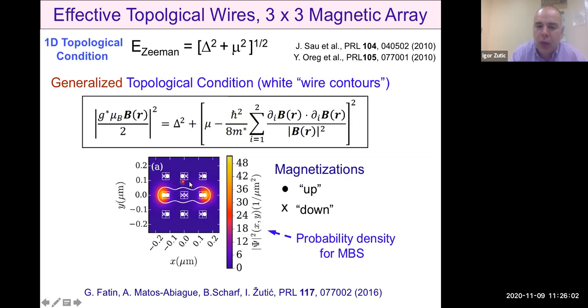And what is shown is now an array of 9 spin valves or magnetic tunnel junctions, where a dot means magnetization pointing up outside of this plane, and X means pointing down into the plane. So we can change, and this is standard procedure in magnetic hard drives or magnetic random access memory, a relative orientation of magnetization in such magnetic arrays. And as we change them, we are also changing the configuration of fringing fields, and we are changing the respective condition that determines where the topological state is present, or in other words, where we have topological and where we have trivial region. And the boundary between topological and trivial region is denoted here by this white contour.